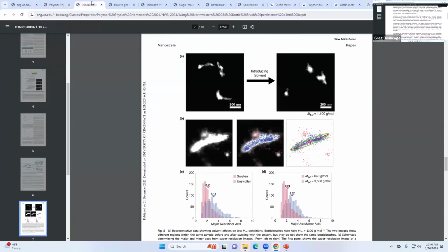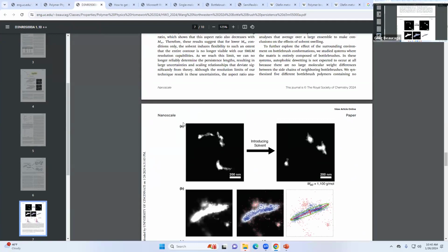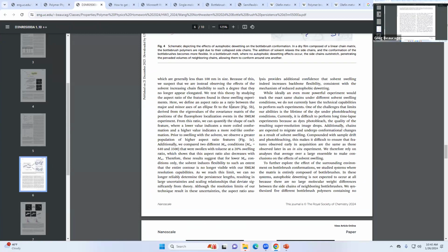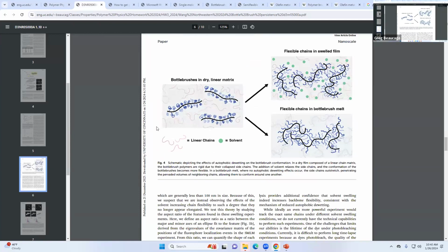And then there's a lot of problems with it, but it does go through persistence. He does calculate that correlation function for micrographs. And so people do use micrographs to get persistence, but they use real atomic scale micrographs. Like if you're looking at DNA, you can see the chain in optical with DNA. But if it's looking at actual molecules, you use AFM to get it. So you have molecular scale resolution, and maybe you can get the persistence from that.